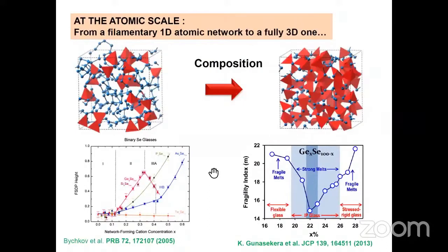The other typical feature is that, as I said, you can continuously tune the composition, starting from a 0 selenium or sulfur network, which has a one-dimensional chain-like structure. And as you add, for example, here in the picture I'm showing for this selenium-rich system, more and more germanium tetrahedra, you basically change from this one-dimensional network, you cross-link it, and you end up with something three-dimensional. Here's GeSe2 on the right side.